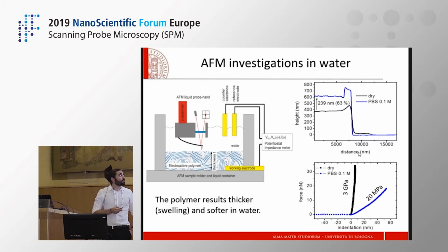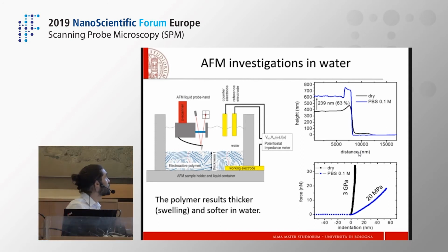Our AFM is able to couple a morphology investigation of our film together with an electrochemical spectroscopy using the film as a working electrode. And in this case, all is done in liquid because we need to understand the properties of the polymer in liquid, which change due to the swelling, due to the uptake of water in the polymer that changes its thickness on one hand and also makes it softer.